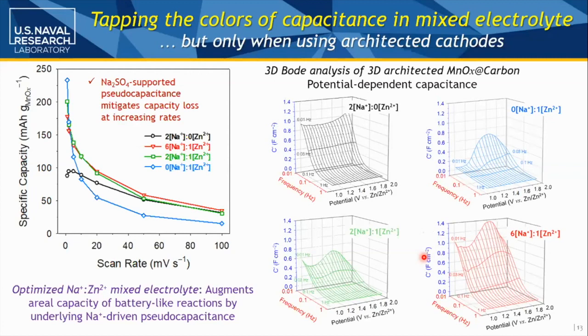You've got a lot of sodium and a little bit of zinc, and you see how nicely you've blended in these two features. You're keeping the real capacitance high, and you're putting in that Faradaic response, which is sort of hinted at here if you look at the capacity as a function of scan rate. The battery looks really good if you're just really slow, but then it's dropping precipitously, whereas the capacitor is less affected at these faster scan rates. So this is an innately hybrid material that you can access because of the ions in your electrolyte.